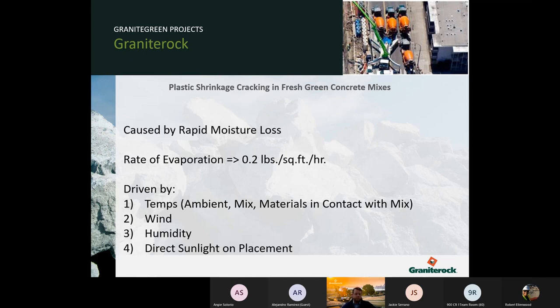What can happen with this slow setting material? The top will dry out first, while the bottom that's not subject to the environment will stay plastic. And once that hardens, it creates a force on the surface that's already hard, creating cracks. So it's something to think about when using green concrete.